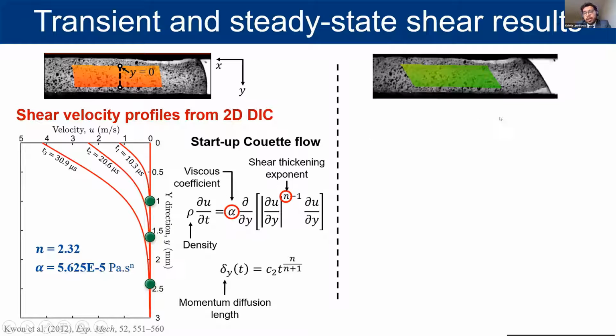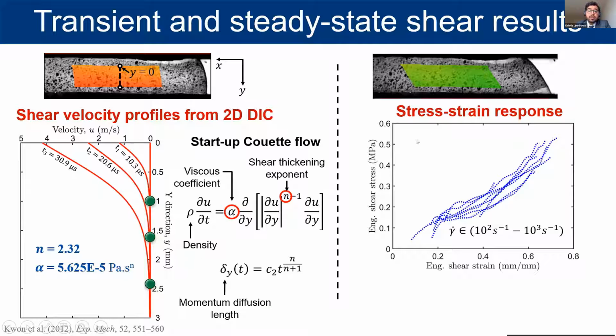Coming to the steady state stage of deformation, in this stage, the stress field has been equilibrated, and finally, we can understand the mechanical response using stress strain data. These are the stress versus strain responses of PDMS from strain rates ranging from 100 to 1,000 per second. Notice that these do not start from origin because this represents only stage 3 response.